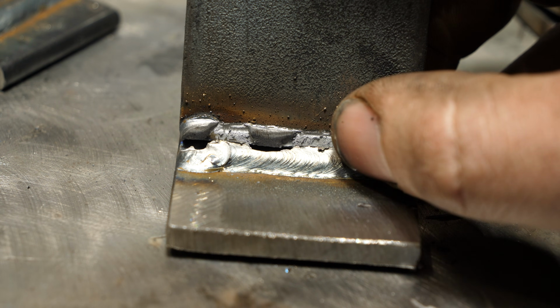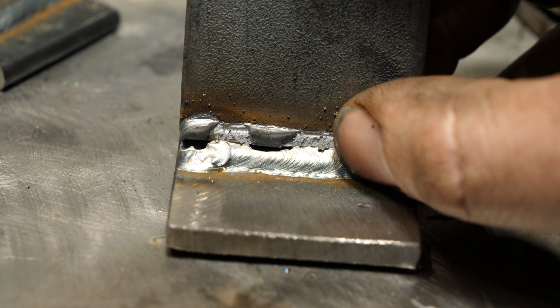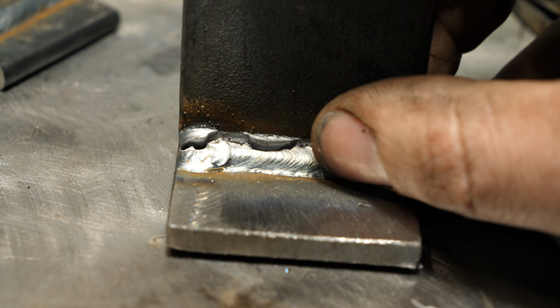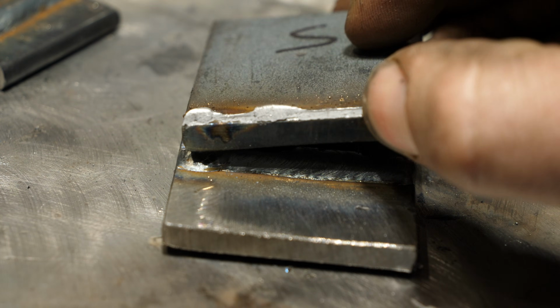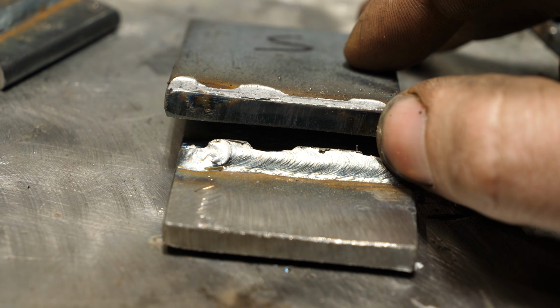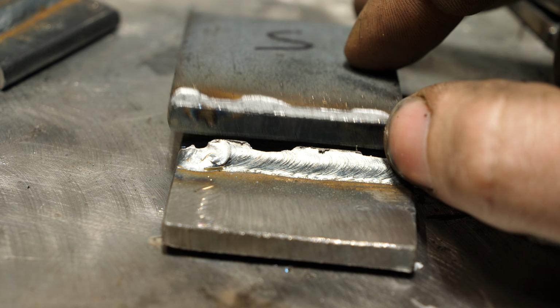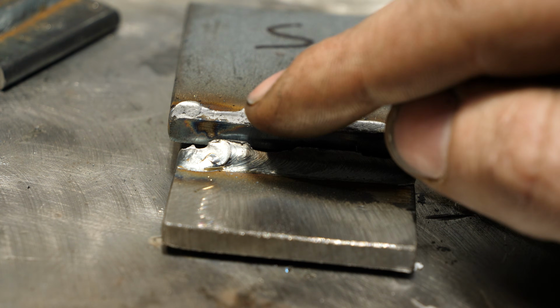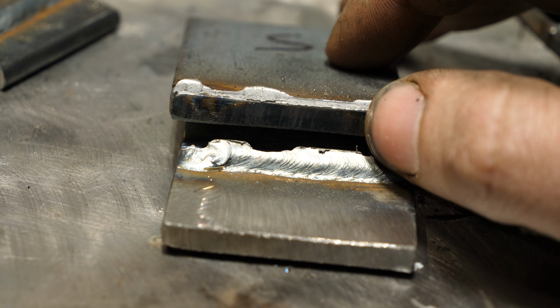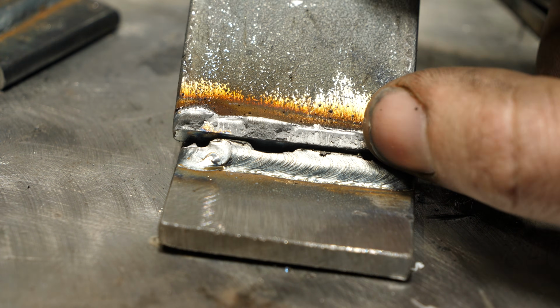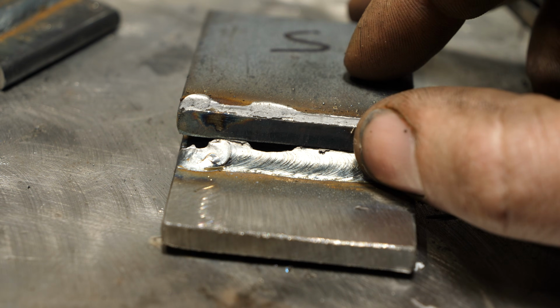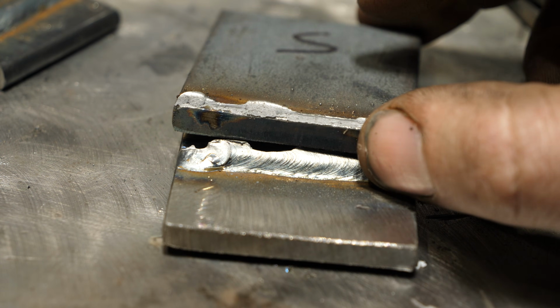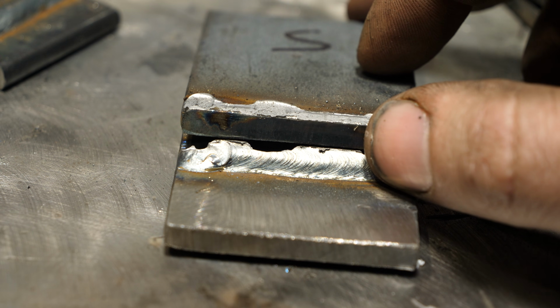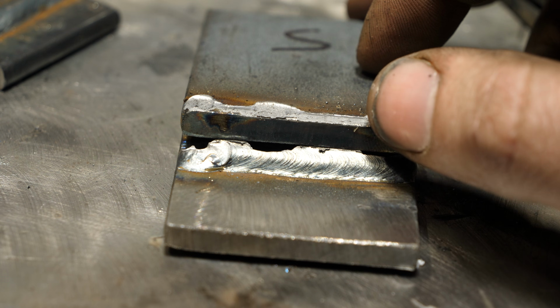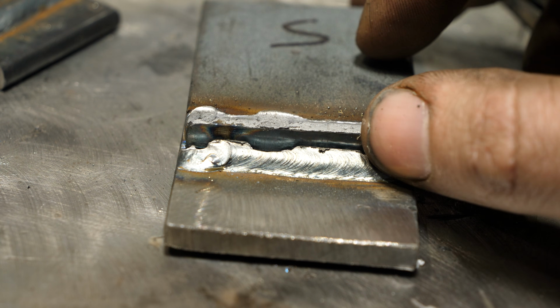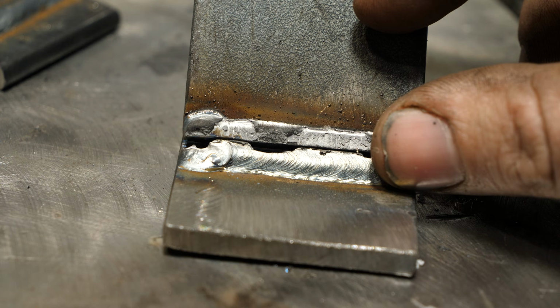So again, MIG does not have very much penetration through a molten puddle, and the thicker the puddle is, the worse off your root fusion is going to be. Now, when you look internally in here, it's basically a completely untouched edge. It got right to that edge, and then that was it. So again, no root fusion, no penetration beyond the root, and poor sidewall fusion. So I would definitely say, again, this is only one test, but straight-in angle, you want to avoid that simply because you have no ability to stay on the leading edge, and the weld's going to be significantly weaker.